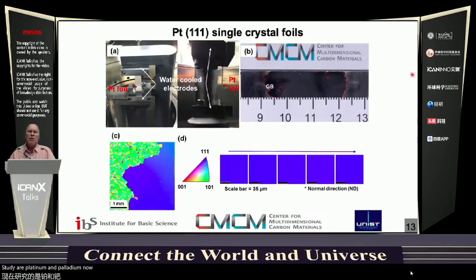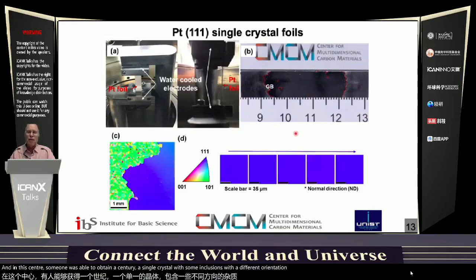Now, in our published work, in that 2018 article, we needed to use Joule heating. So we ran an electric current and resistively heated, I squared R, a central portion. So this is where the water-cooled electrodes were clamped. And you can see this is polycrystalline. And in this center, we were able to obtain essentially a single crystal with some inclusions with a different orientation.